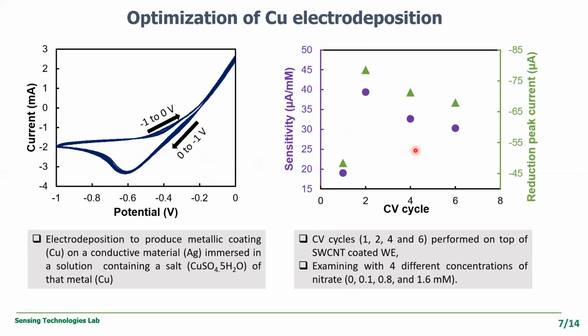In the next figure, we optimize the CV cycle. Here we have applied a total of 4, that means 1, 2, 4, and 6 CV cycles to electrodeposit copper, and each electrode was tried with 4 different concentrations. Those are 0, 0.1, 0.8, and 1.6 millimole.